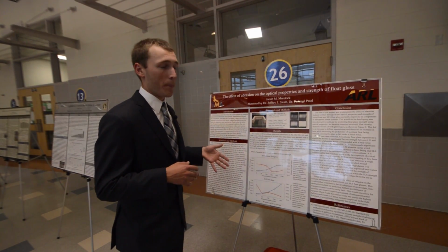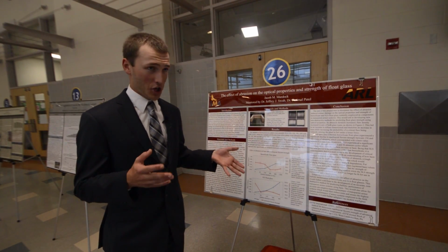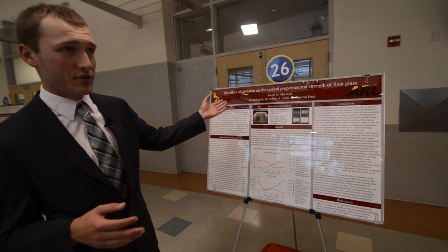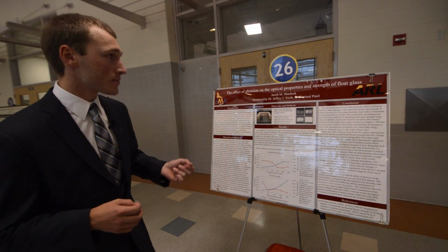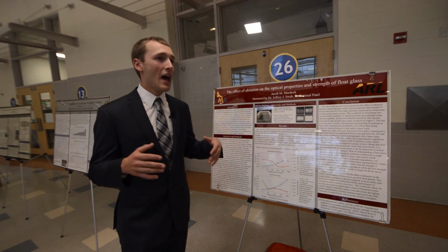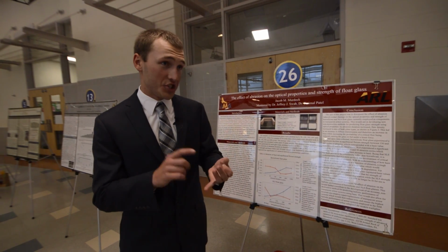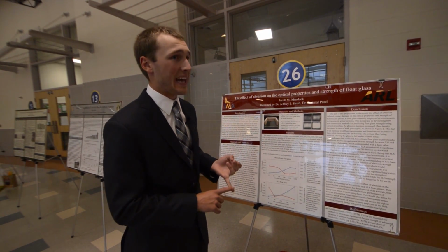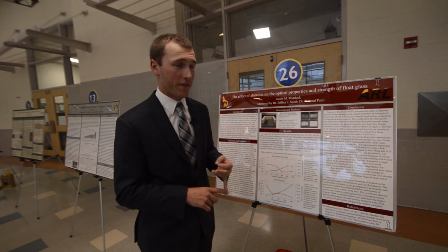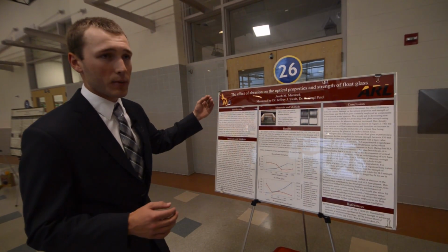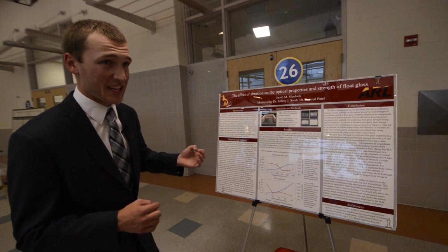My goal is to develop a non-destructive method for determining the strength of float glass, and we will do that by using optical properties. We found from the beginning that as we induce flaws in the glass, the flaw is not only changing the strength, but also affecting how light passes through the glass and therefore affecting optical properties. The optical property that we chose to focus on is haze.